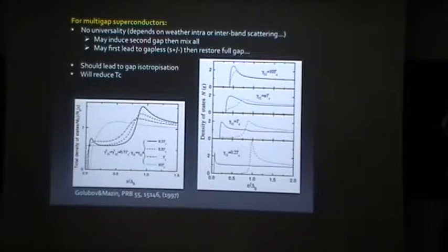For instance, could it be that the E2g phonon is responsible for interband scattering too, or do we not know? I don't think it's this phonon mode. From my understanding, it's really the most important phonon mode to address for superconductivity in MgB2. But for the other one, basically, you need to interpret it. The difficulty with MgB2, and it's not very clear to me, is that it's very anharmonic. The spectrum is really completely anharmonic, and in such a case, I don't know what it means for the coupling.